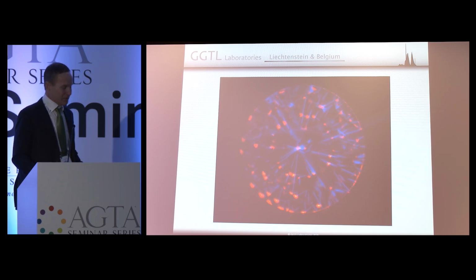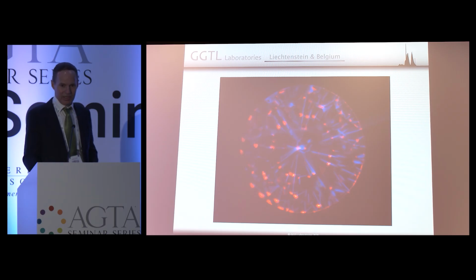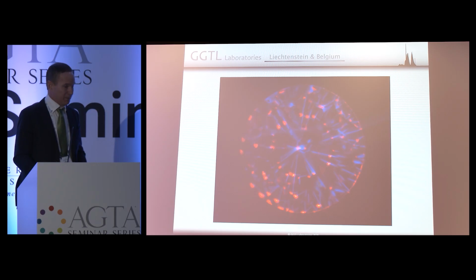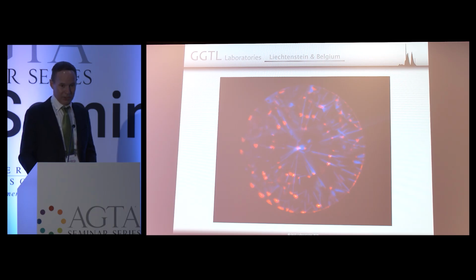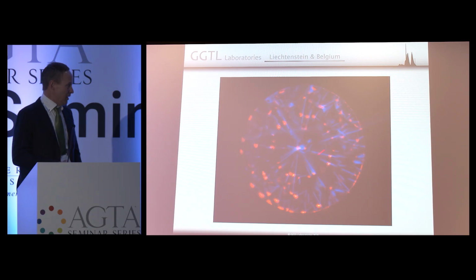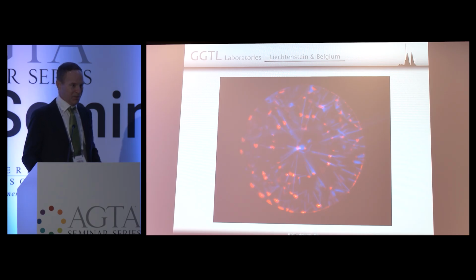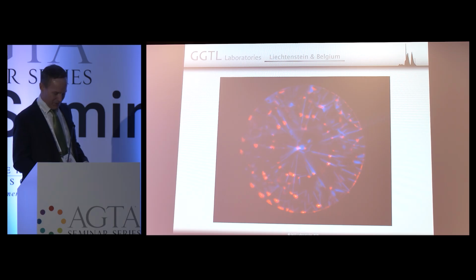Corundum. So this is one of the rare diamonds that contain a corundum inclusion. I think there were actually maybe 2 or 3 of them in it, not just one. But I hit one of them that was reflecting throughout the stone, this one here. So this one was exactly at the culet, so it was already reflecting on all the stone. What did I do? Focused laser beam, hit the inclusion, and there you have it, glowing all throughout the stone. So this is a corundum inclusion in a colorless natural diamond.